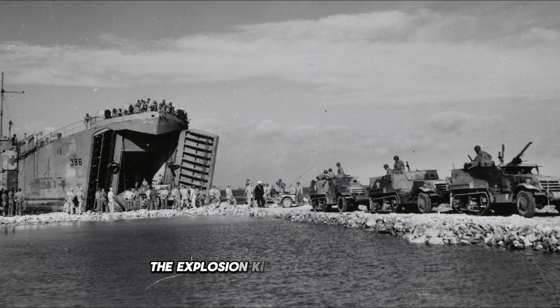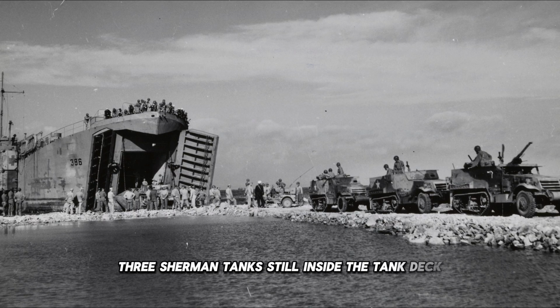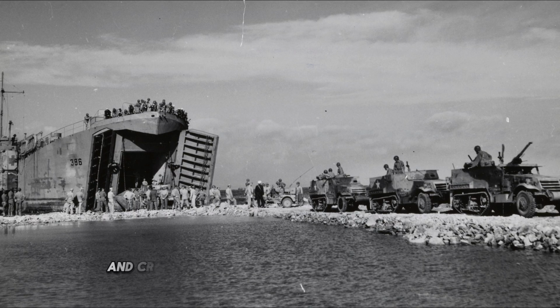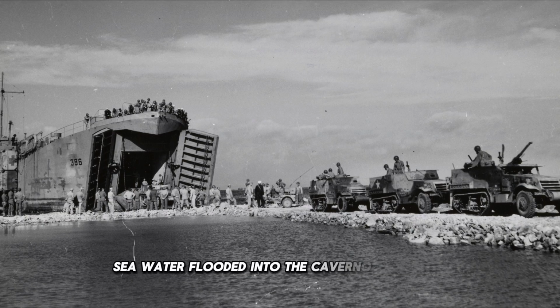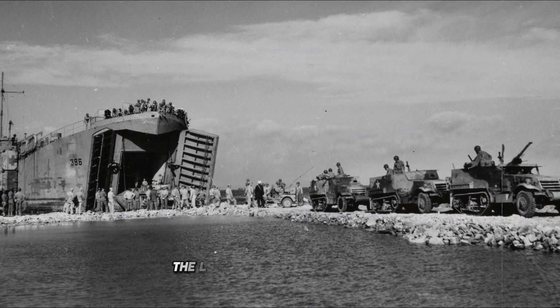The explosion killed 11 men instantly. The bow doors, each weighing 4 tons, were blown completely off their hinges and disappeared into the Mediterranean. 3 Sherman tanks still inside the tank deck broke loose from their chains and crashed through the starboard hull plating. Seawater flooded into the cavernous interior at roughly 2,000 gallons per second. The LST-317 settled stern first into 12 feet of water within 4 minutes, blocking the beach approach for the next 3 landing craft in the assault wave.